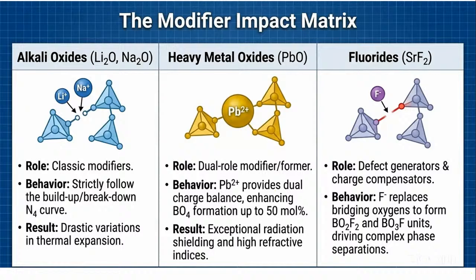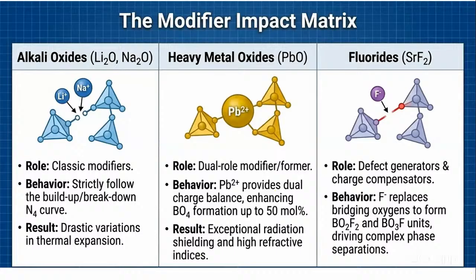And if you're looking at the heavy metal oxides, they play a very dual role where they are having a role of 50-50 chances where they can become a modifier as well as a former. So, for example, if I have to come up with high refractive index glasses, or if I have to come up with high radiation shielding glasses, I would definitely go with the lead oxide or a bismuth oxide for this particular matter, or even barium oxide, which also falls into the alkaline earth category, but still it is a heavy metal. So therefore, they also play a very crucial role in this particular phenomenon of shielding glasses.